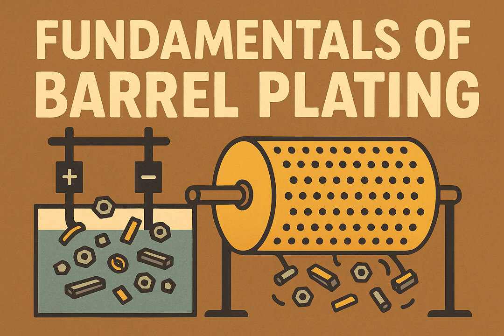What if the color looks off or it's uneven, blotchy or dark? Dark or uneven color is often a sign of metal contamination in the bath, frequently caused by drag-out carrying metals from previous tanks, like copper from a copper strike bath contaminating a subsequent nickel bath. Contamination again. Minimizing drag-out is crucial, and sometimes electrolytic treatment, called dummy plating, can help remove metal contamination from the tank. Other causes include poor pretreatment or base coating, too low current density, a low concentration of the main plating salt in the bath, or poor electrical contact to the parts.